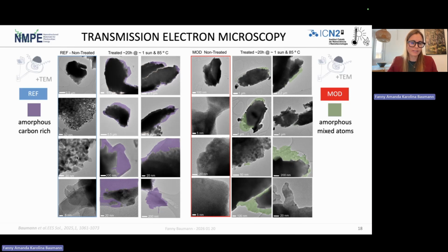And we could see that for the non-treated sample, we could clearly distinguish grains, but for the treated sample in the reference case, we really saw that there's this amorphous substance around areas with perovskite. And in the modification case, we saw that there are again clearly distinguishable grains both in the before and the treated samples. So we can see that there's just a little bit of some new material created, but it seems to have a quite different morphology than the material created in the reference.